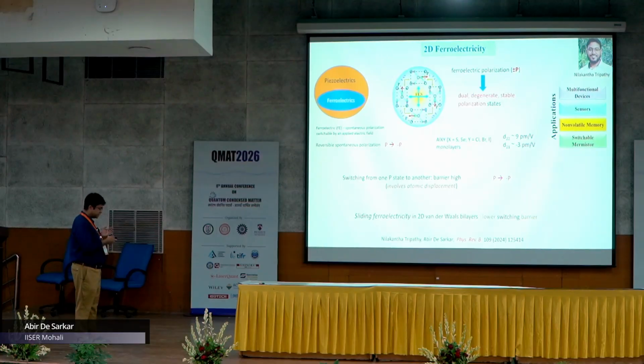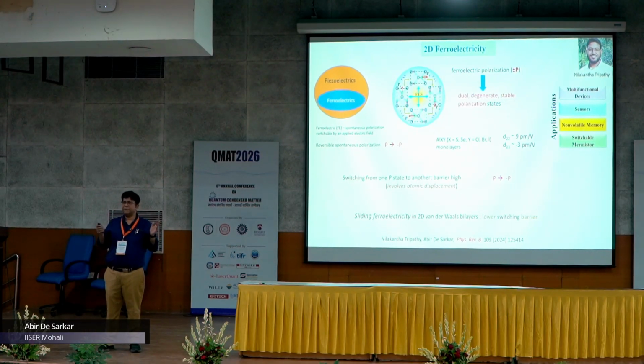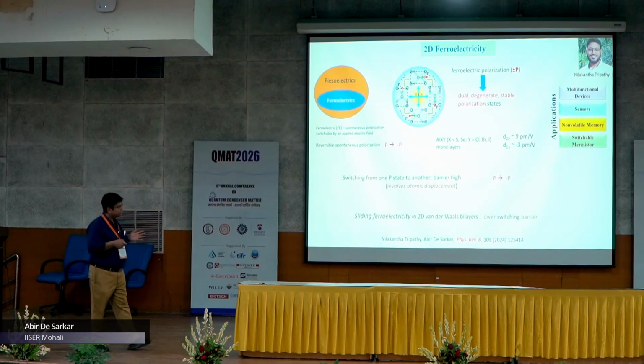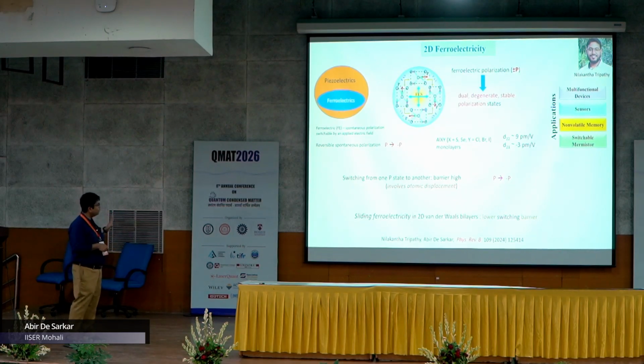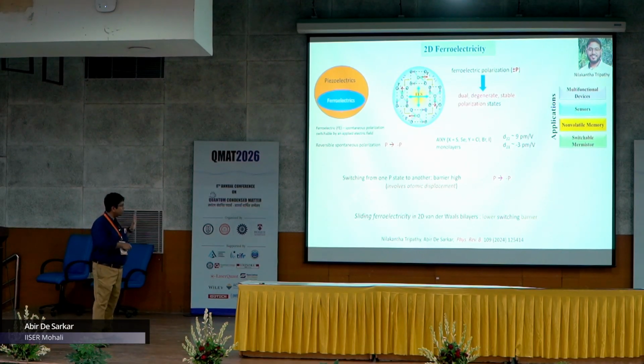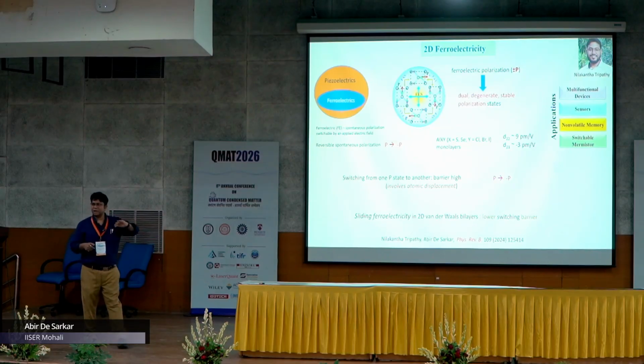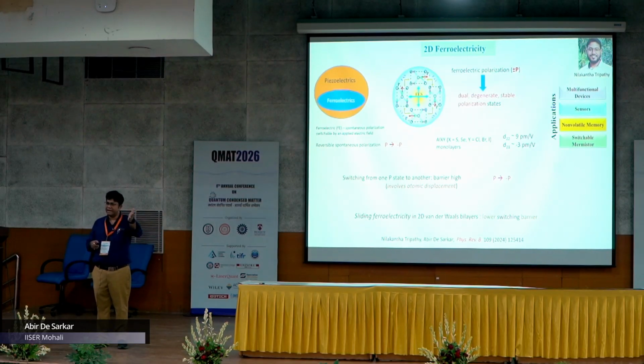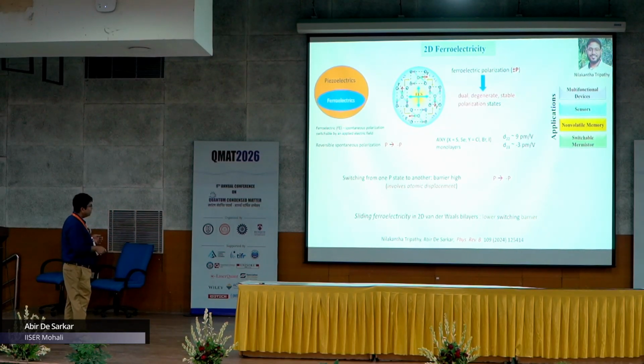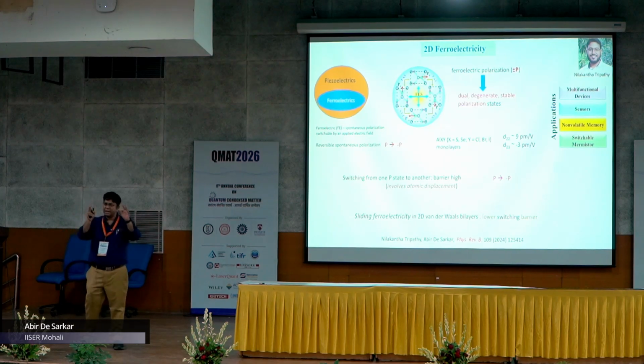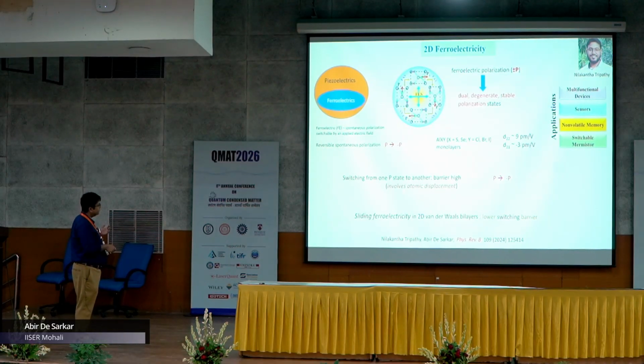And so, this plus P and minus P can play the role of zeros and ones in electronics, and can be used to encode information. So, therefore, they can find useful applications in non-volatile memory devices. Now, in a single monolayer, if one has to switch from one P state to the other, one has to transcend a high barrier. The barrier is very high because it would involve atomic displacements and a structural reorganization within a single layer. That is the reason the barrier is high if you have to switch the polarization direction from plus P to minus P.